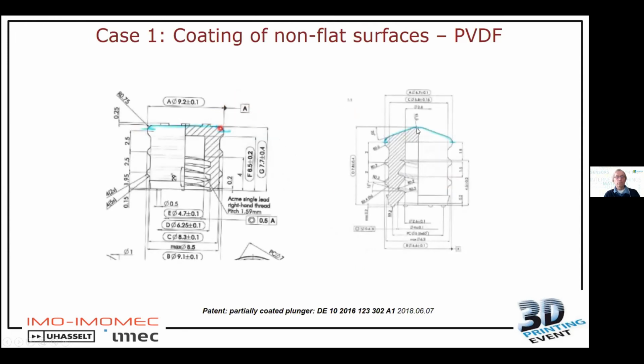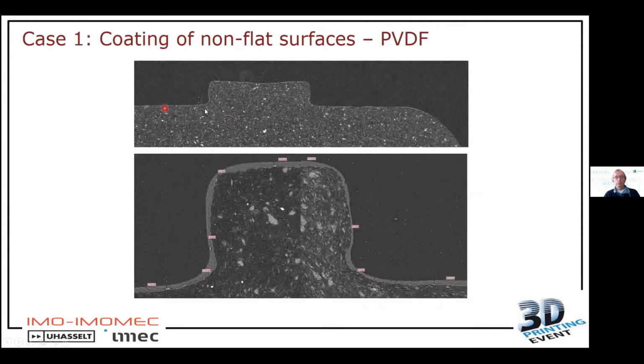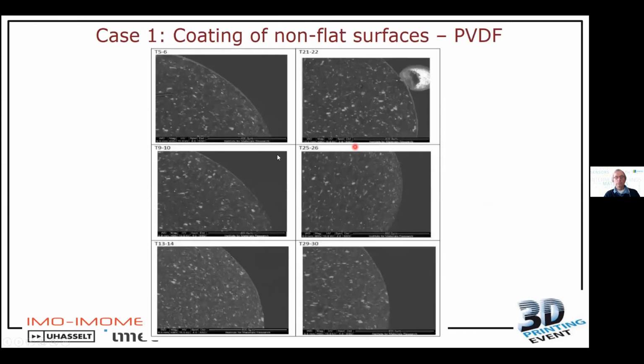So you see this plunger and this plunger. And what we would like to achieve is that the liquid doesn't flow in here, but only stays on top. And that's shown here. So this is the top where you see the coating. Also here, a zoom where you see the coating on this thing. But if you then look in detail and you go lower into these fringes, you don't see the coating anymore. So this shows that you can have selective coating on 3D objects.